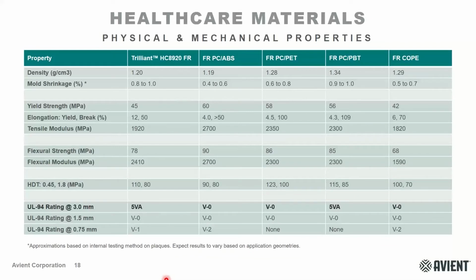And so how does the Trilliant material compare to some of the incumbent materials in the space? This is an example of the properties for our flame retardant grade, 8920, compared to some other FR PC alloys as well as FR copolyester. So one of the things you might notice off the bat is that the mold shrinkage is a little bit higher. And so these materials are made out of an aliphatic polyketone blend. And so that polyketone imparts some crystallinity. And so being semi-crystalline, again, it'll tend to have a higher mold shrink, much more comparable to something like a PCPBT. In terms of the tensile and flexural properties, you'll see across the board that these materials are in the